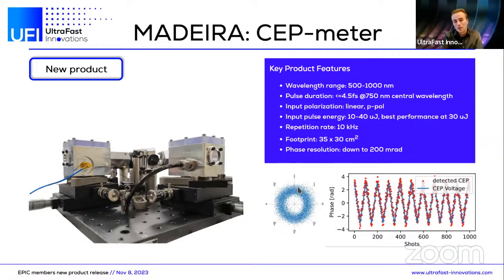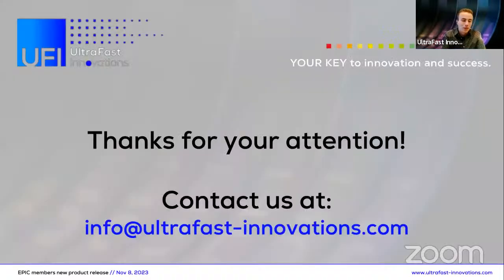And when using this device, in addition to a reference, you can verify that the measurement data of this device corresponds to the carrier envelope phase. And it comes with the advantage that our device is sort of a one-to-one replacement to other commercially available devices, but with a much simpler approach, because previously the use of ultra-high vacuum was necessary and some MCPs. But our device is now measuring a similar or the same quantity with a much simpler approach, which makes it much more reliable in comparison to what has been on the market before. And with this, I would like to conclude and thank you for your attention.